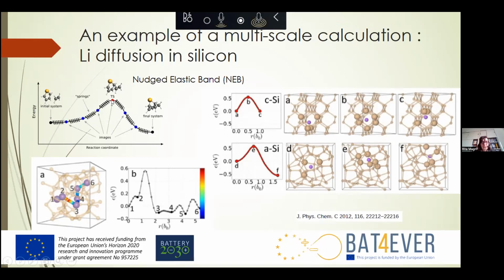This allows us to calculate the activation energies for the processes as a difference between the energy of the transition state and the energy of the initial state. So, this is the energy barrier that the system has to overcome to finally arrive at the final situation. I have used this method also for studying chemical reactions catalyzed by some catalyst, studying the development from some reactants to some product and calculating the activation energy for the chemical process. But it can be used also to study diffusion, such as lithium diffusion in silicon. For example, here are positions of the lithium atom inside crystalline or amorphous silicon.